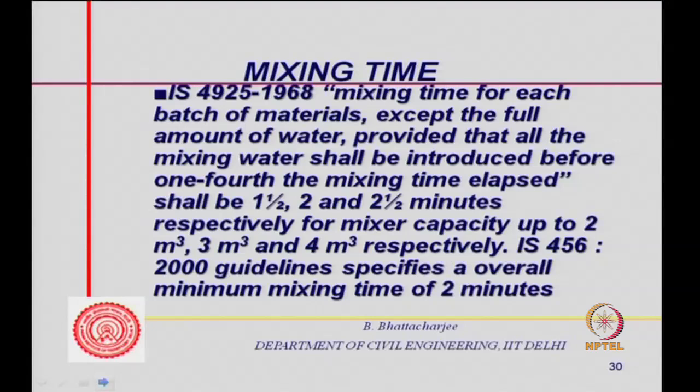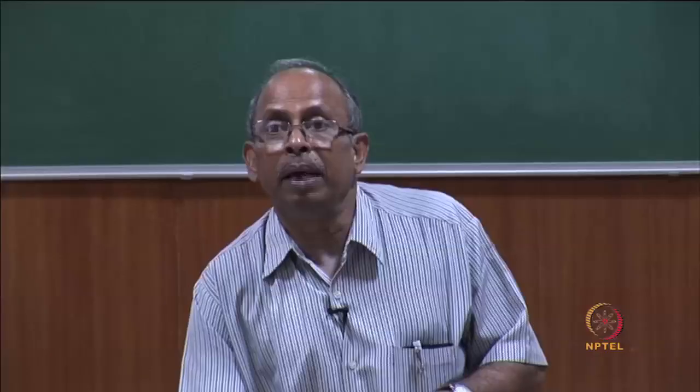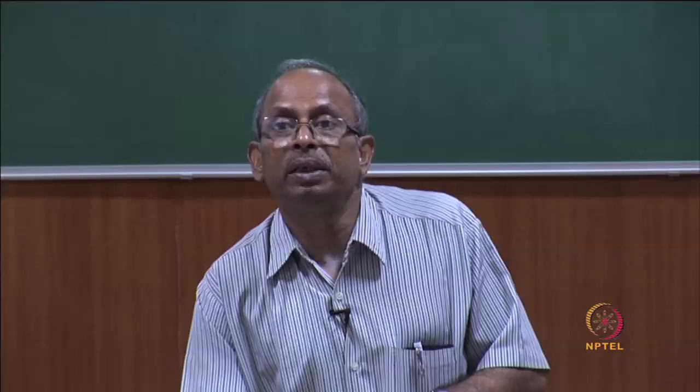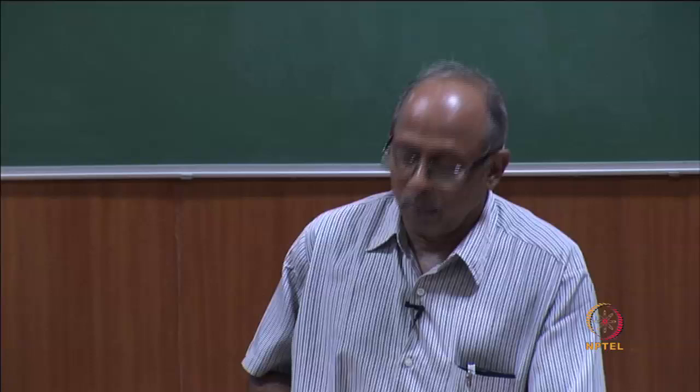But then the other one, 4925, tells you 1.5 minutes for 2 meter cube, same as what I said earlier, and for 3 meter cube 2 minutes, and for 4 meter cube 2.5 minutes. So, these are the mixing times, but we will see the basis behind all this.